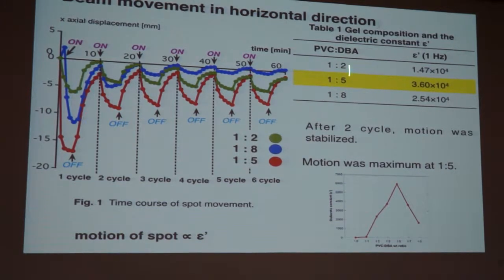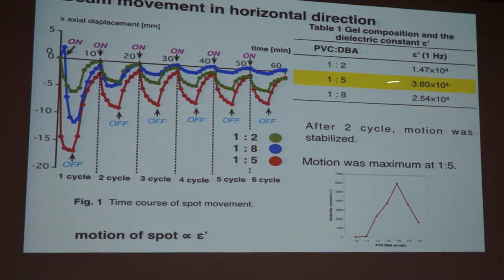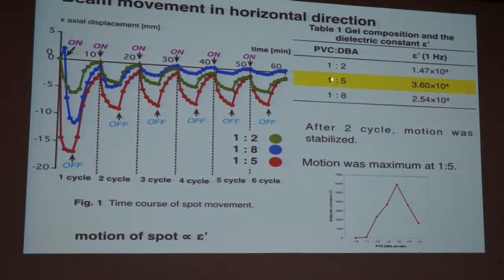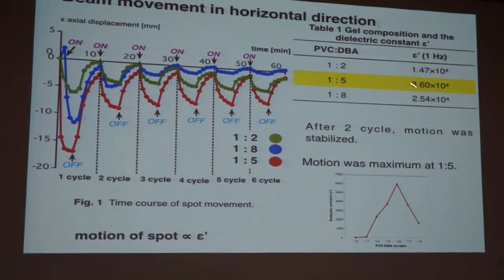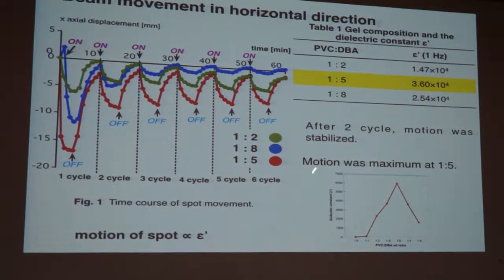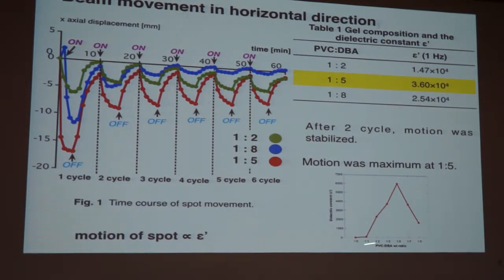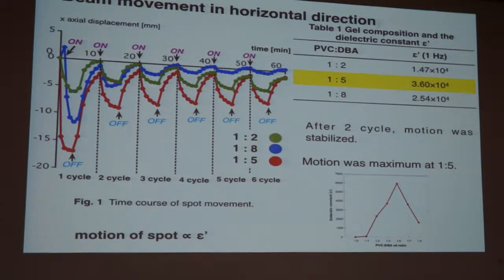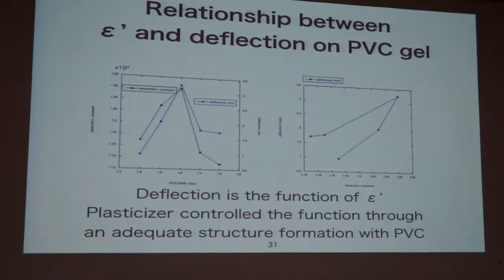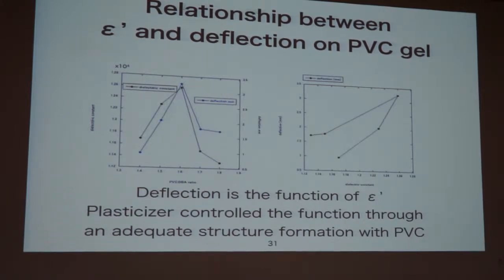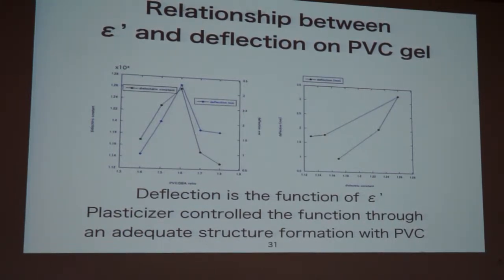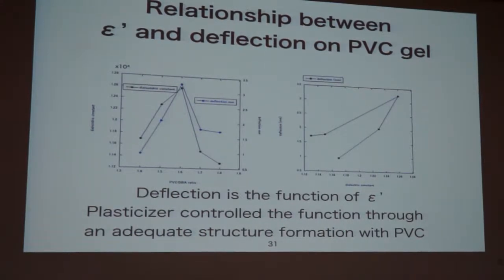And as shown in the other slides, at a certain composition of the polymer and plasticizer, the deflection is amplified to a maximum in this system. So it's again suggesting that the larger the dielectric constant, the larger the deflection angle. This is the same way. Deflection angle is a function of epsilon prime, and plus we can control the function through adequate structure formation. What structure is formed in the gel is not clear at this moment.